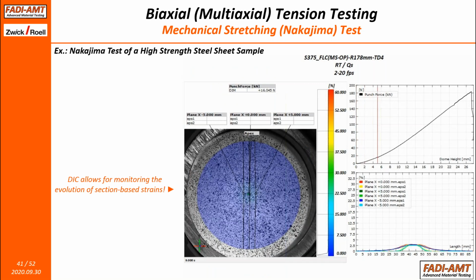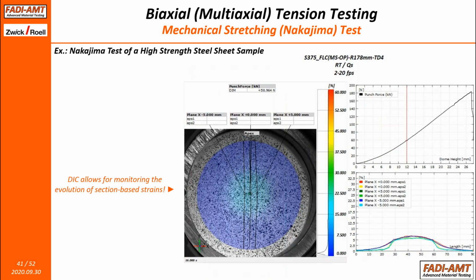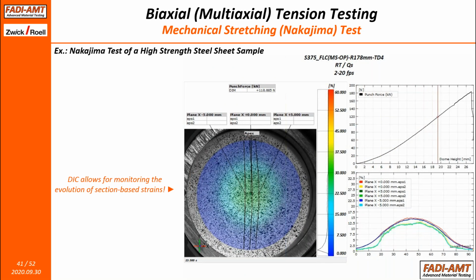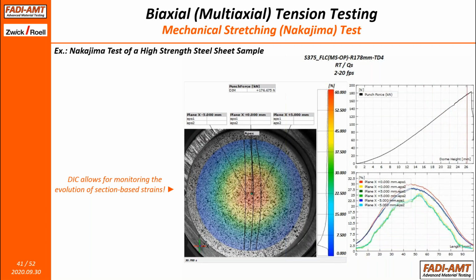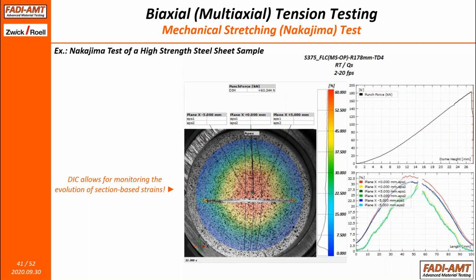This is another example where DIC is the only option to get really meaningful output out of the test. So it's a similar test. In this case, though, we are monitoring the section distribution of strains. And you can see those sections in my video on the left-hand side. They're vertical black lines that represent virtual sections. And on the right-hand side, we can see the distribution of those sections or section strains. And that is necessary in order to generate an FLC by the ISO method. And without it, you cannot generate it by the ISO section method.